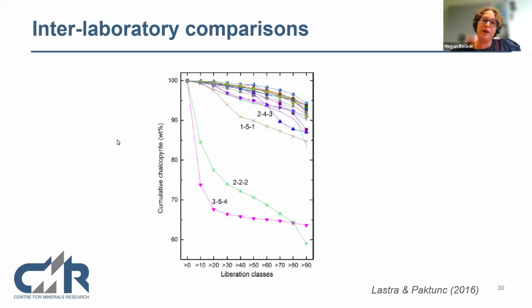Then they wanted people to look at liberation. And the majority of people, this is cumulative liberation yield again. So here are the liberation classes. That's the cumulative chalcopyrite yield. Most of the groups were sitting over here, but there are definitely a few outliers. In this case, the 354 pink group said there was a lot more unliberated material than there was. And same for 222, where most people are saying it is mostly liberated, which considering it's a chalcopyrite concentrate, one would expect the liberation to be quite high. So this is just an idea of some of the variability that the measurements can have.